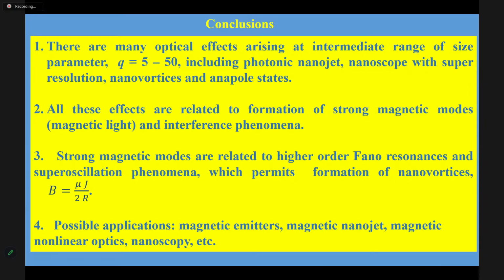In conclusion, I want to say that there are many optical effects arising at an intermediate range of size parameter, Q from about 10, including photonic nanojet, nanoscope with super resolution, nanovortices, anapole states also. All these effects are related to the formation of strong magnetic modes, magnetic light, and interference phenomena. These strong magnetic modes are related to high order Fano resonances and super oscillation phenomena, which permit the creation of nanovortices with very high magnetic intensities.